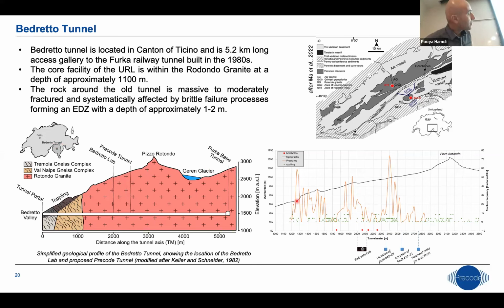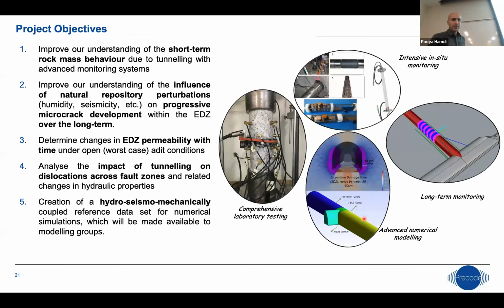What we have observed is that as we pass through the tunnel, as the amount of overburden increases, we can see clearly a sign of spalling on the existing Bedretto tunnel. So we know that the amount of stress acting there is quite in favor of spalling. It's below the strain bursting, which is good for us because we can have a controlled deformation. And it's beyond the crack initiation level. That's a really good setting for us to be able to do our tests.